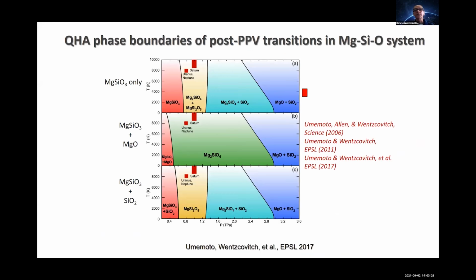Ten years of research led to this phase diagram that I'm showing to you. Post-perovskite decomposes into a magnesium-rich and a magnesium-poor phase. And then the magnesium-poor phase exsolves silica, and you're left only with the magnesium-rich phase, which finally decomposes into the elementary oxides at around 30 megabar. In the presence of magnesium, you don't have the magnesium-poor phase, only the magnesium-rich phase. And in the presence of silica, you have first only the magnesium-poor phase, and then it proceeds to evolve in silica, etc.